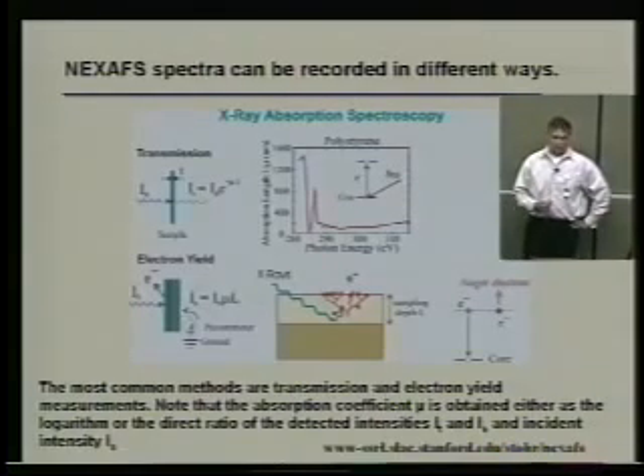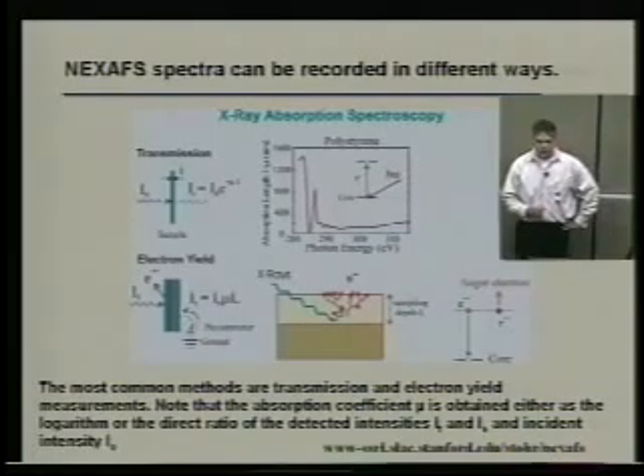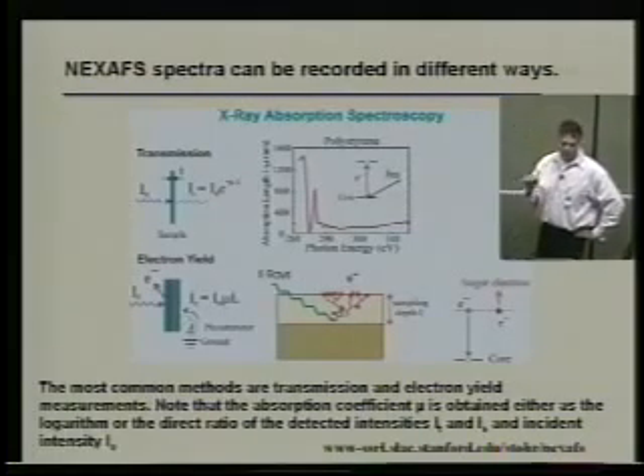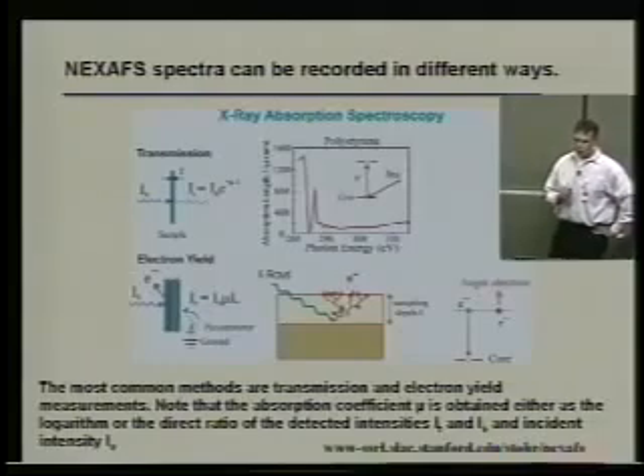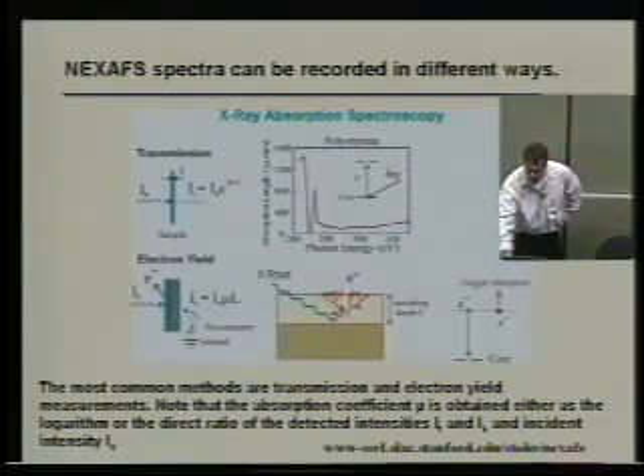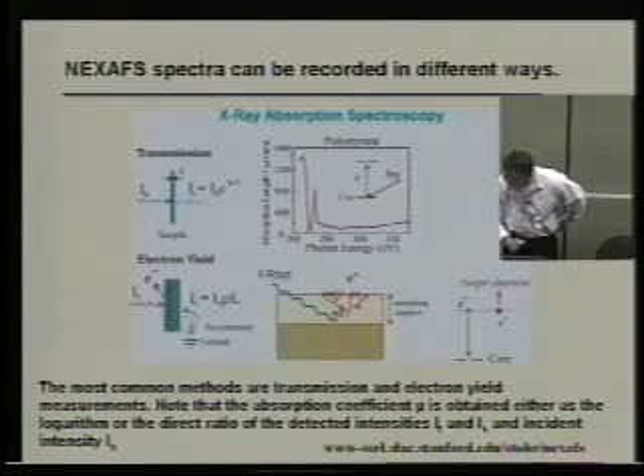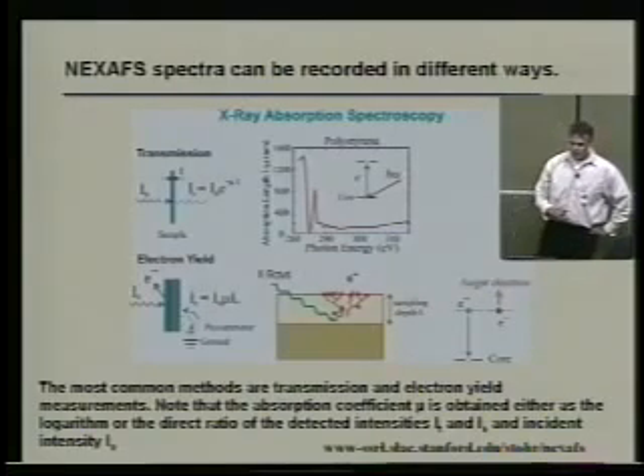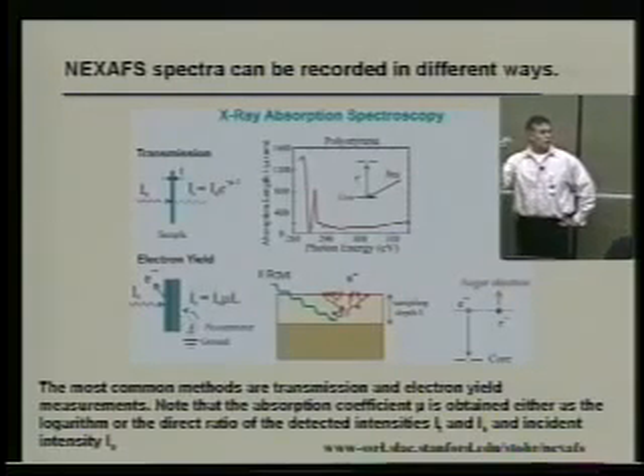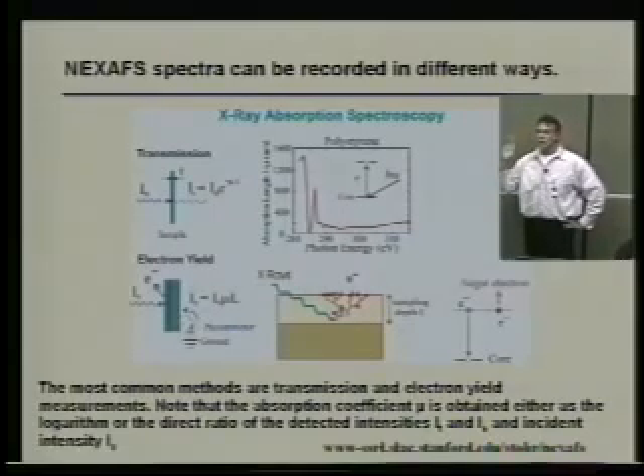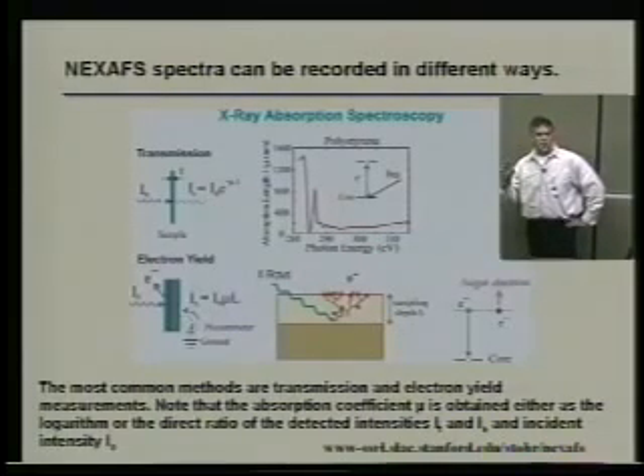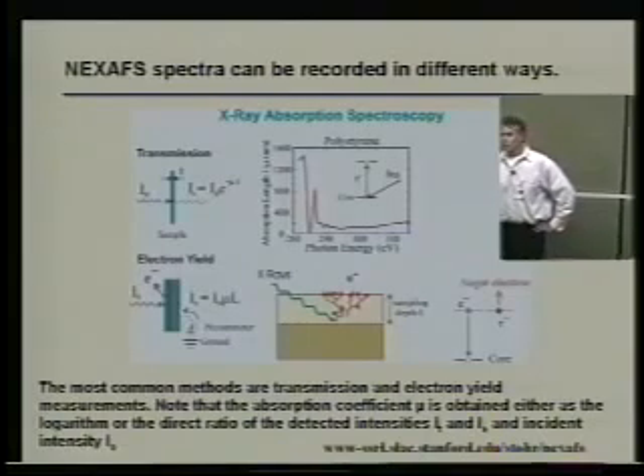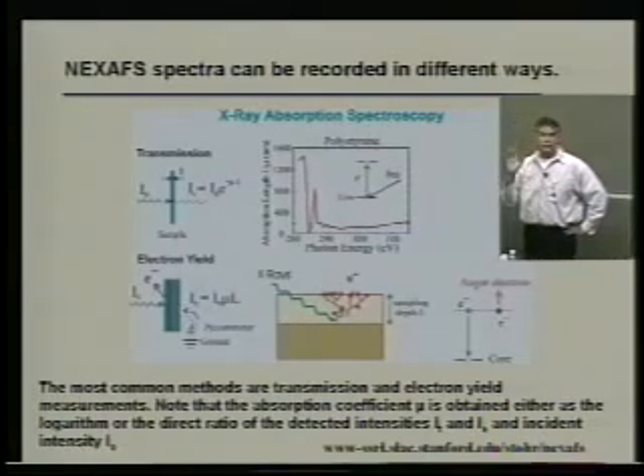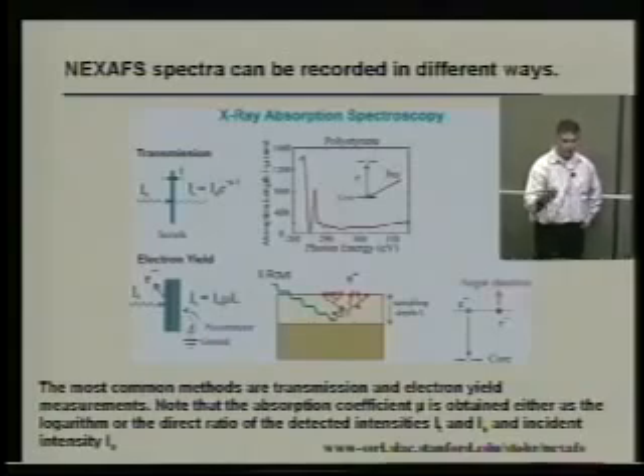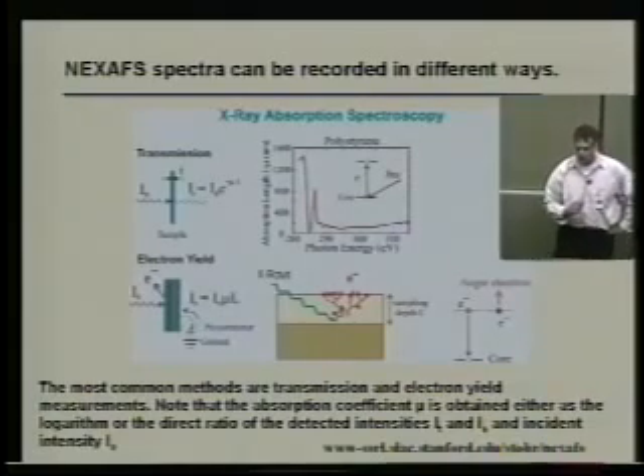A more common way of looking at the near-edge structure is electron yield. In this case, you shine incident X-rays on your sample, and you create a core hole, as in the diagram in the bottom corner of the plot. So you form a core hole, and then an electron from a higher level falls down. You get an Auger electron ejected. The Auger electron can interact as it goes out with valence electrons, and you get a cascade of electrons coming out. So you actually get a whole bunch of secondary electrons, which is shown in the plot in the middle.